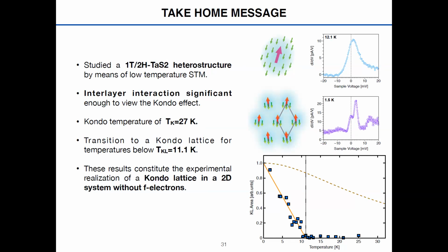So we've studied a 1T-2H tantalum disulfide heterostructure by means of STM. Although it's a van der Waals heterostructure, the interlayer interaction is strong enough to produce this Kondo effect between the localized moments at the center of the Star of David cluster and the itinerant electrons of the 2H phase. We find a Kondo temperature of 27 Kelvin, and then we're able to measure the transition to a Kondo lattice that occurs more or less at 11 Kelvin. So therefore, we are realizing the 2D Kondo lattice in a 2D system without any f electrons, as happens in other heavy fermion materials.